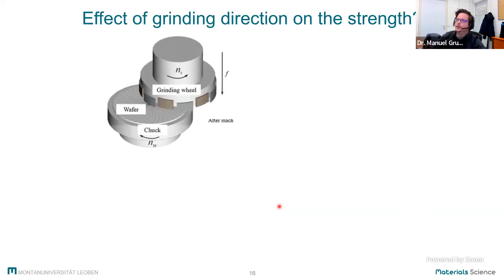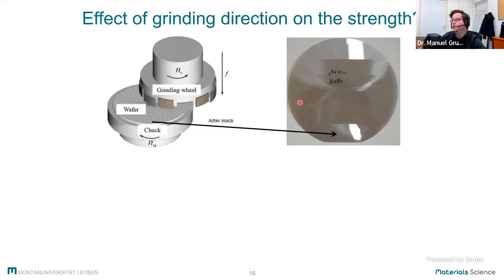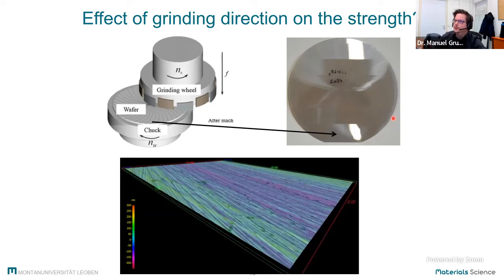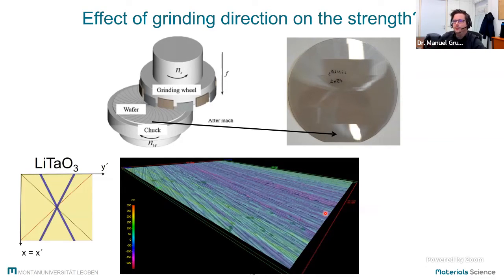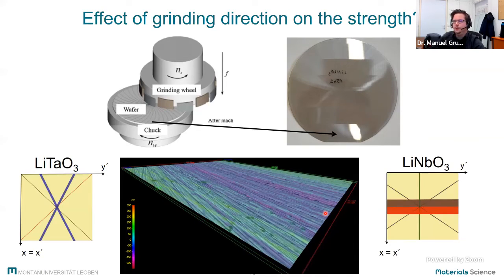Then we had a closer look at how this roughening process looked. Due to the rotation of the grinding wheel, we get grinding grooves going from the center to the edges of the wafers. So we have all kinds of different orientations for these grinding grooves on the surface of our single crystals. And if we think of the small dimensions of our devices, these grinding grooves can be considered parallel on the surface of the single crystals. Now we wanted to know if there is an influence whether the scratches are parallel or at a certain angle to the cleavage planes, and how this can affect the strength of our material.